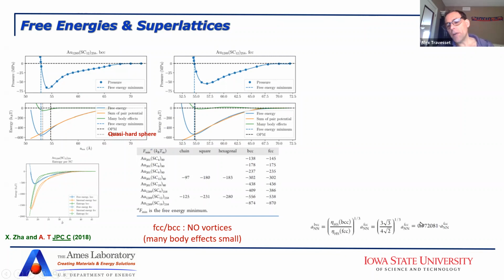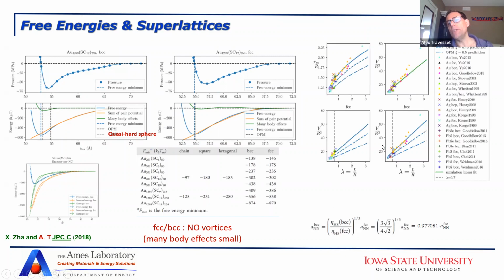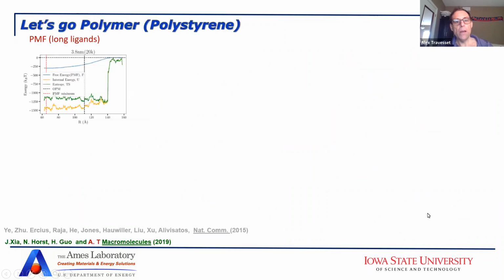There is also another effect that has to do with the BCC, which is that the BCC and the FCC for these systems end up having the same packing fraction. And this is something I'm not going to describe in detail, but basically, the results are in good agreement with the experiment. And this transition from FCC to BCC, we are not the first to find it. It was already described by Lutke and Landman many years ago for single component lattices.